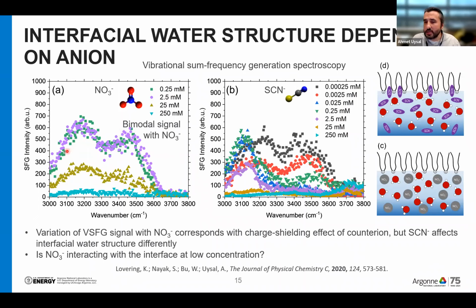As your ions adsorb to the surface, they shield the surface charge. Also, they disrupt the hydrogen bonding network of water molecules. So this signal goes down. This is a very typical way of understanding how your ions are adsorbing to the interface. Very similar to what we have seen in the organic phase, there's a qualitative difference between nitrate and thiocyanate. As you can see, with nitrate, the signal goes down, and that's it.